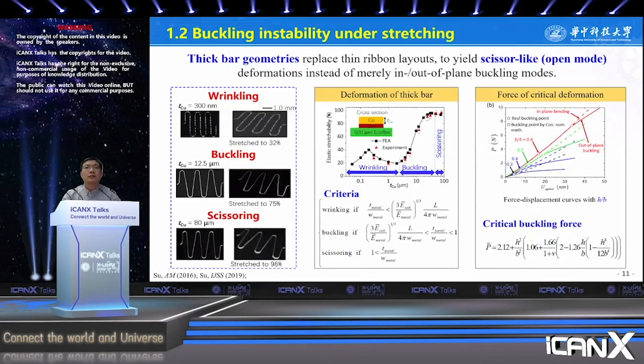On the other hand, the serpentine structure will also buckle when stretching. We can observe from the left figure that the thickness determines the deformation mode. The thick bar geometries are used to replace the thin ribbon layout to yield open-mode deformation instead of merely buckled mode. It is more suitable for highly stretchable electronics. In the middle box, three regions of deformation occur in this range: wrinkling, buckling, and scissoring. The scissoring is stable deformation.